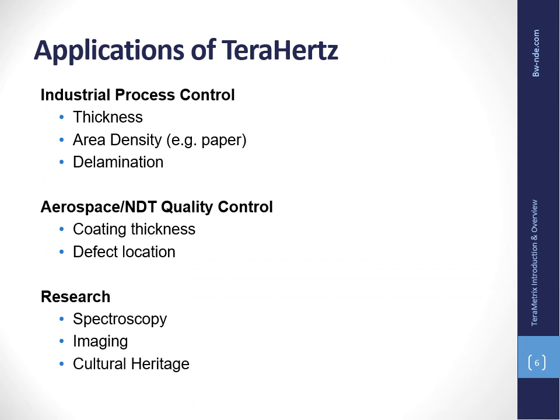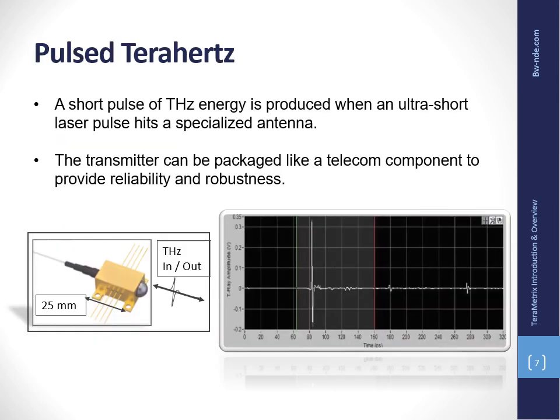There are many applications of terahertz radiation and more are being developed. In industrial process control, it's used to measure the thickness of non-conductive materials. It can be used to correlate the strength of the reflections to area density, for example, in measuring the weight of paper. It can be used to detect delaminations between layers. In aerospace NDT, it's being used to measure coating thickness and to locate defects in high technology materials. There are also many research applications of terahertz radiation, such as spectroscopy, which we'll talk about a bit more later, various types of imaging, and it's also been used in a number of cultural heritage applications, for example, measuring multiple layers on paintings. The single point gauge is configured to allow the measurement of up to 3 layers simultaneously. Different recipes or programs can be selected to evaluate different products. The next video shows this being used for measurement of a 3-layer fuel tank.